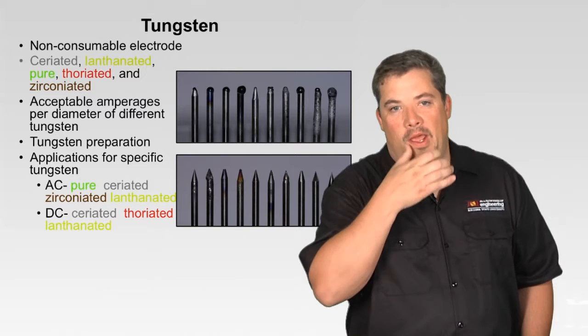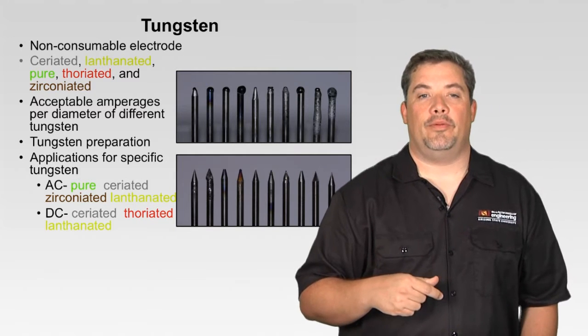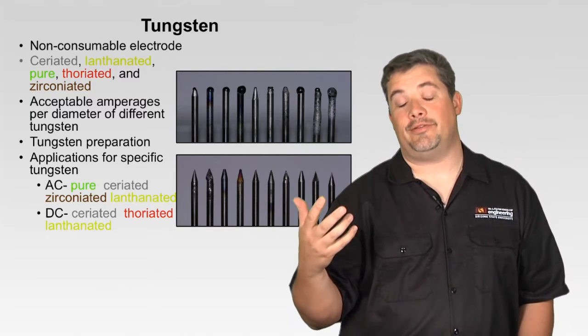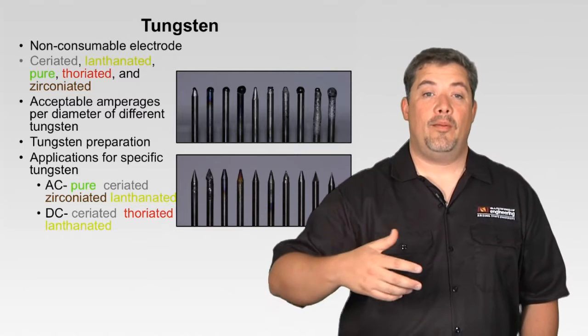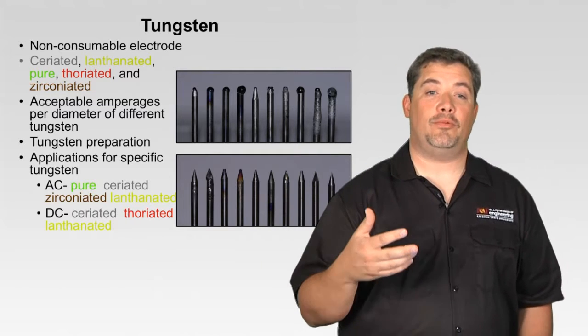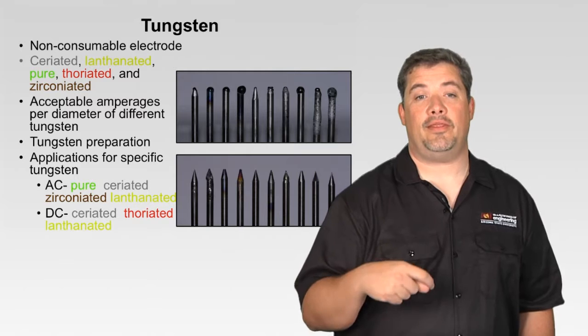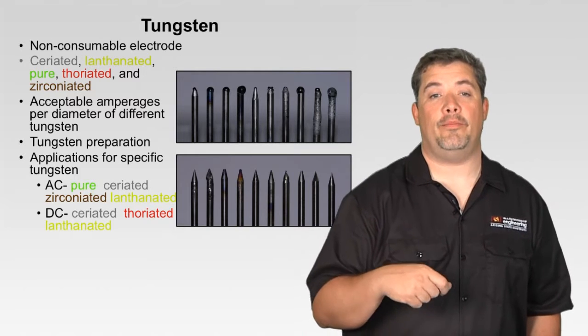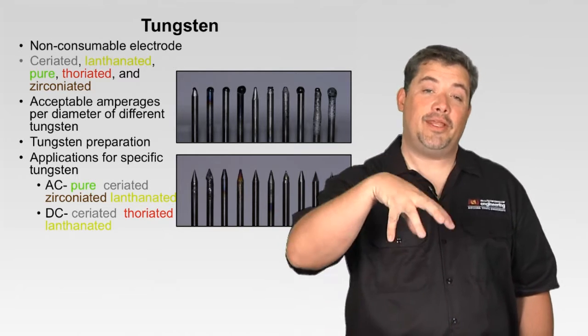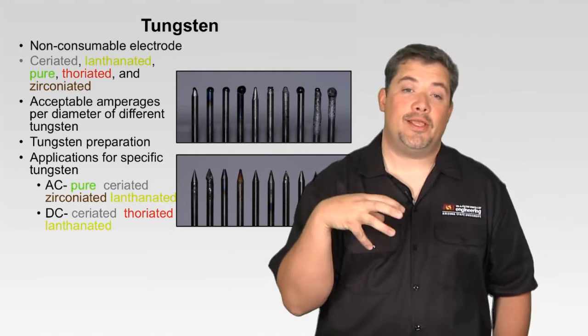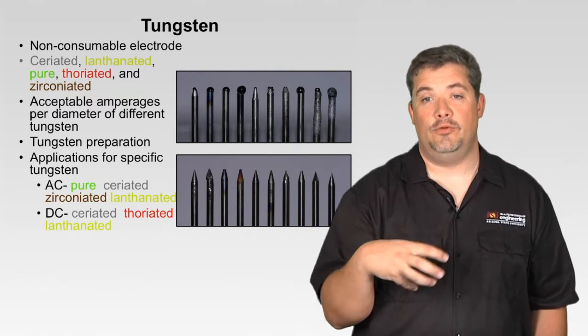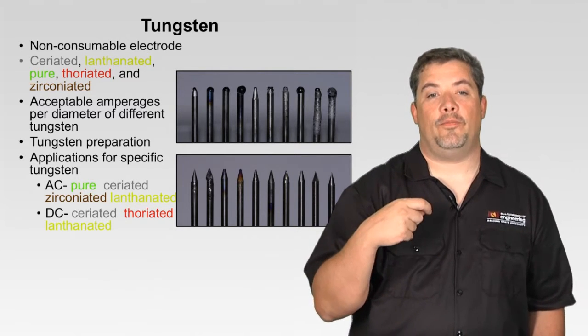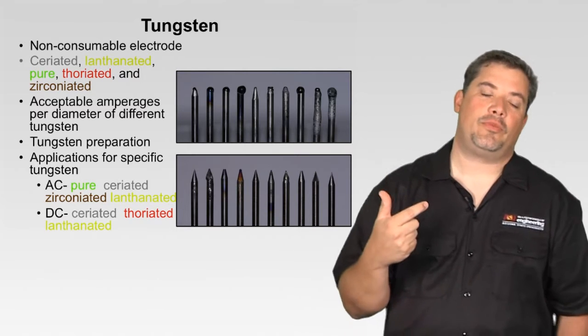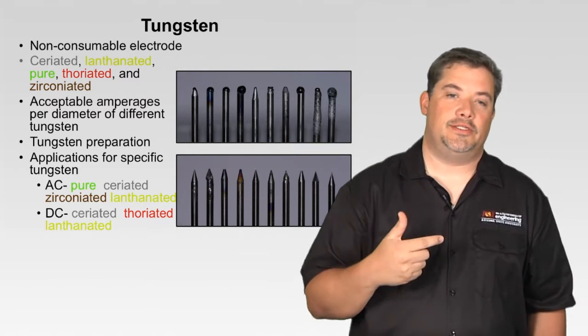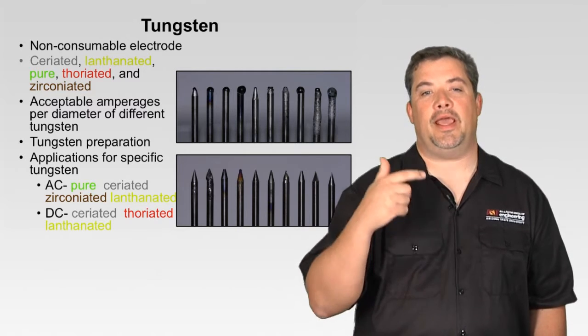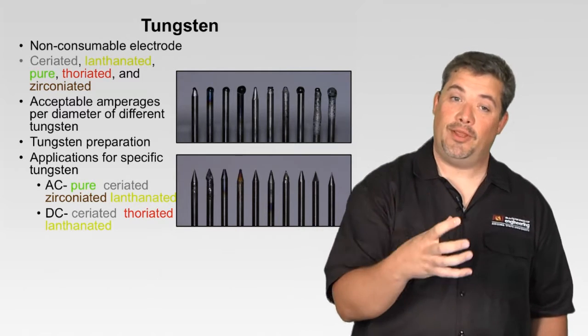So tungsten, it's our non-consumable electrode. Why tungsten? Tungsten has a very high melting point. And when we alloy that tungsten with alloys like cerium and lanthanum and zirconium and thorium, it elevates their melting temperatures even better. So it makes them even better to use for TIG welding. There's a certain bunch of tungstens that we use for different applications, and the size of tungsten really makes a difference as well.